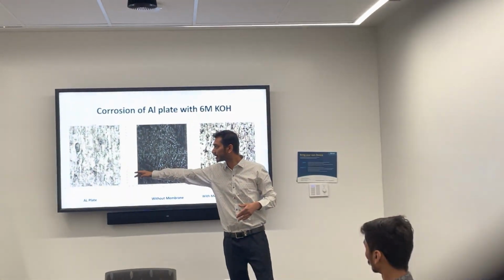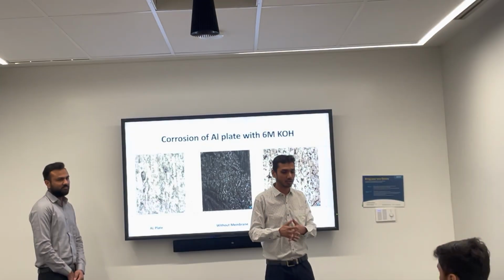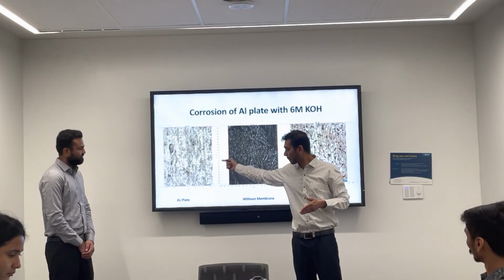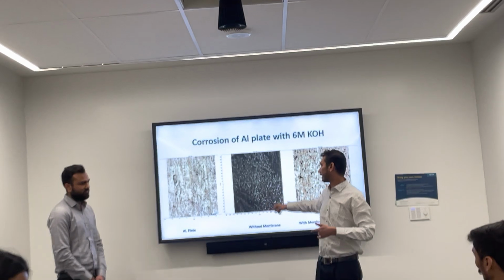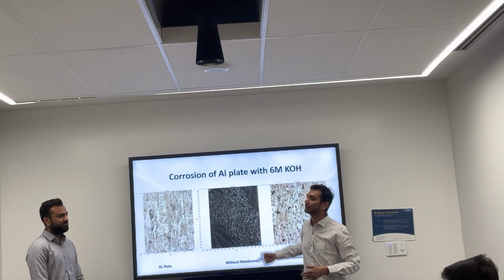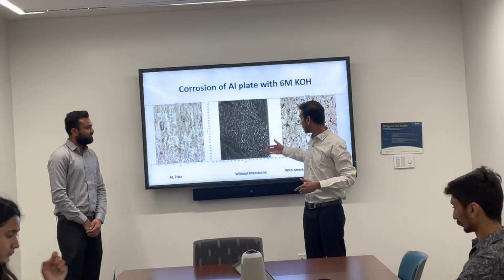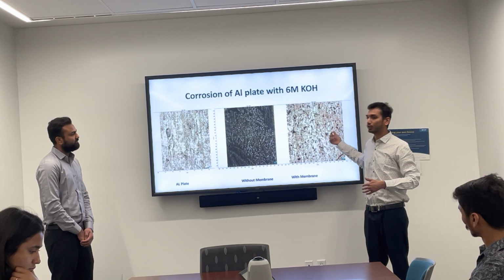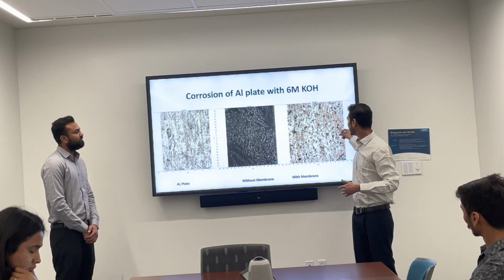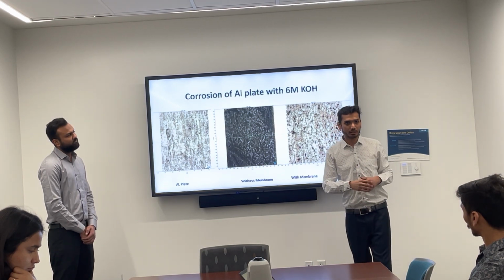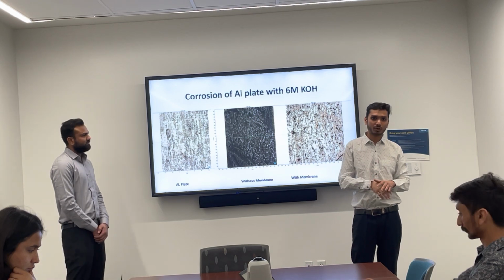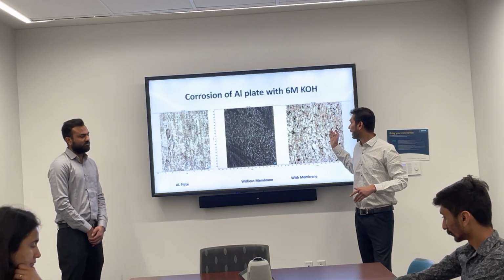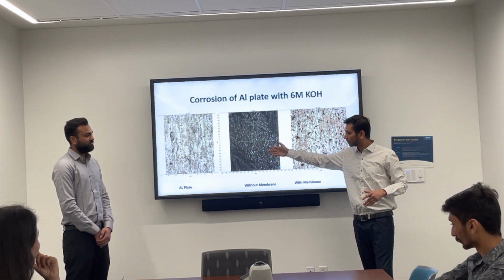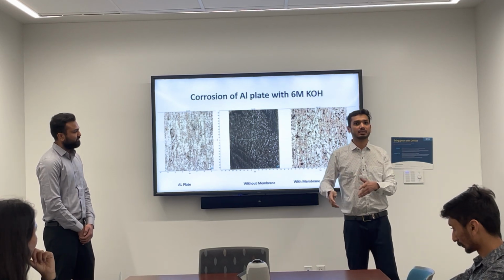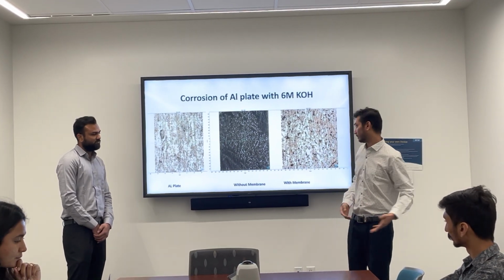But here there is an aluminum plate before the reaction, when it's new and non-reacted. The first photo is the microscopy of the fresh aluminum plate, and the second one is without the membrane. You see it's completely dark. There is no place for the reaction to go on here. The next one is with the cellulose membrane, and here you can clearly see that there is one black spot. That's the already reacted part of the aluminum plate, and it's not reacting now. But here there is much more space, better than the one without the membrane. That means the aluminum plate still has more potential to give more power with the membrane.